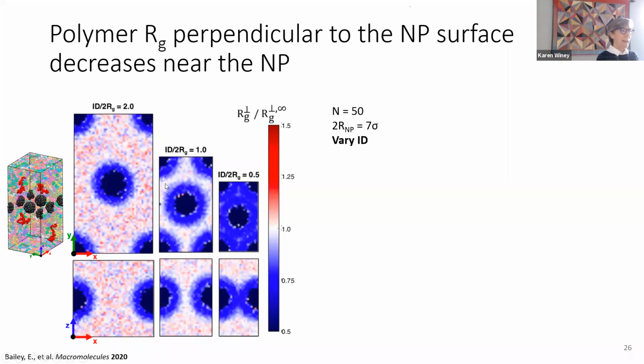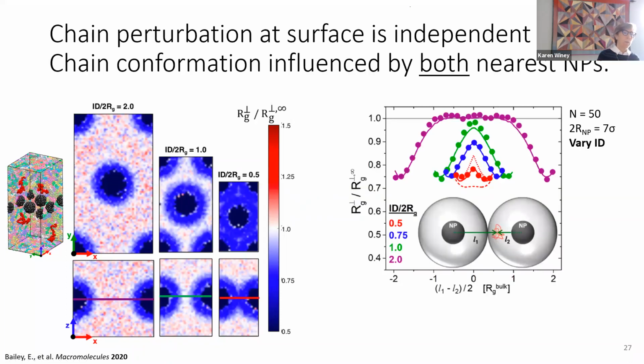Right? And what's interesting is the thickness of this compression is independent of the interparticle distance. It's really just about the particle. And that's more evident here when we take these line traces across and then plot the radius of gyration perpendicular to the surface relative to the bulk. And up against the wall, it is always the same, about 0.75. And then when the particles are far enough apart, it's compressed at the wall, and then it goes back to the bulk level, and then it goes compressed to the next wall. So that would be this one, where there's some compression here, then it's like the bulk, and then it's back to compressed on the second particle.